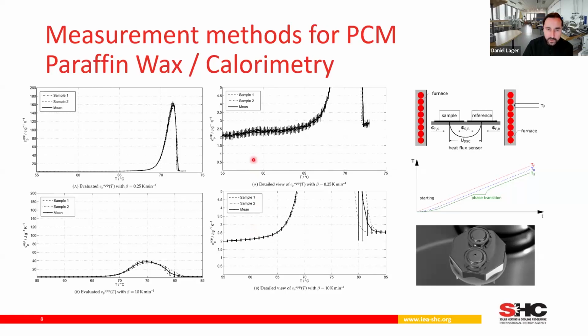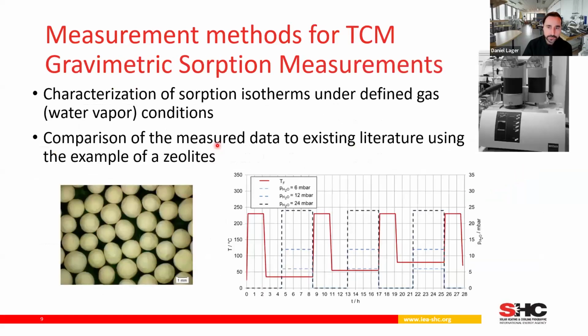And the comparison of these two measurement procedures shows that you cannot use every procedure for every quantity. For example, I would not use this procedure to analyze a specific heat capacity because the uncertainty in that region is pretty high. So for specific heat capacity, I use fast heating rates. But if I want to analyze a temperature where the phase change occurs, like here at 70 degrees centigrade, I would use lower heating rates to get a better temperature signal in comparison to faster heating rates. This should show the influence of the heating rates in calorimetric measurements.